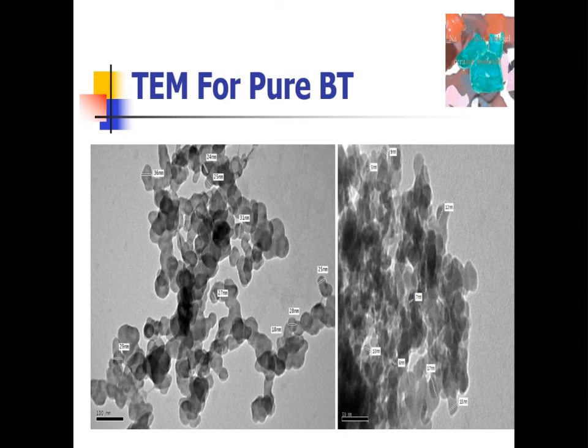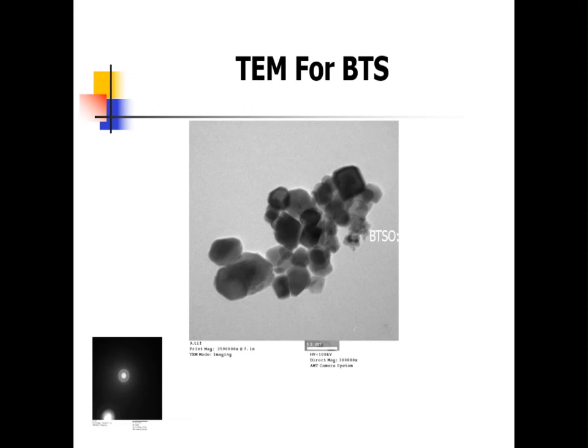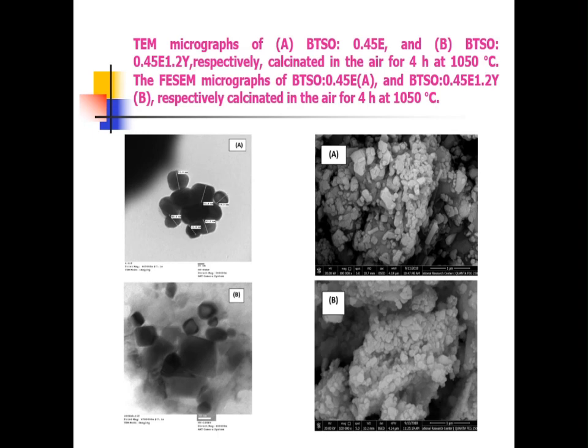We studied the transmission electron microscope of the barium titanate, which gave us a homogeneous sample with no accumulation, and informed us about the nanostructure and the particle diameter, which begins from 18 up to 36 nanometers, no more. Then the sample is in nanoscale. And here is the transmission electron microscope of the sample doped with tin oxide, the barium titanate doped with tin oxide and doped with erbium ion, and doped with erbium and ytterbium ion.